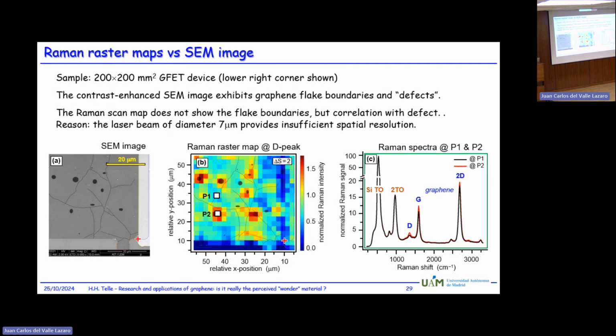Here's one example where we have compared an image generated by SEM. SEM has a very high resolution. You see here, probably not from the distance, some black lines in the picture. These are grain boundaries of the graphene. In contrast to the belief of some theoreticians that you can produce graphene ad infinitum, in reality graphene only grows in small chunks, which are then joined together, and you see these boundaries. In addition, you see a few black spots here. These are not defects in the system, but dust grains on top of the surface.